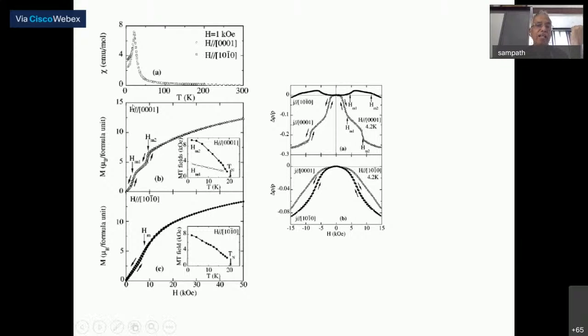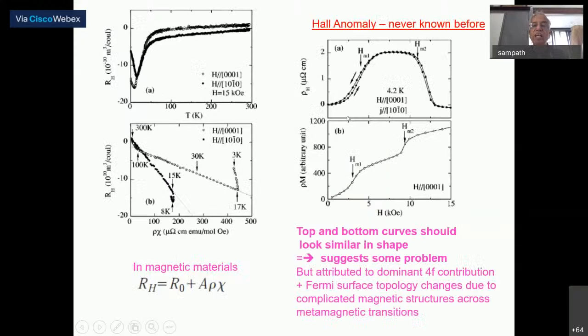And first of all, in the magnetization, you see the 2 metamagnetic transitions here. Magnetization as a function of field, there are 2 transitions here. Now, across these 2 transitions, you see a magnetoresistance drop, a very huge value here. Now, we measured the Hall effect on this. This is what is very surprising. If you measure Hall resistance as a function of field, it goes up at the first metamagnetic transition field and drops at the second metamagnetic transition field. And look at the value, it's very, very large.